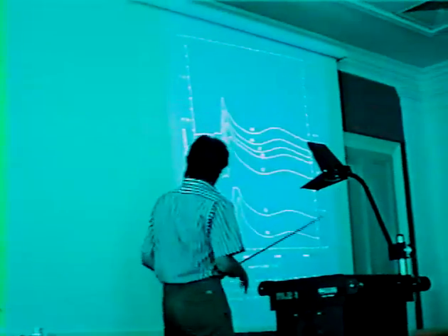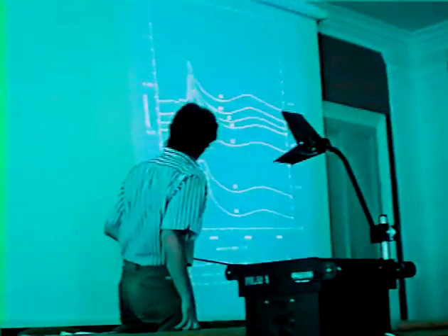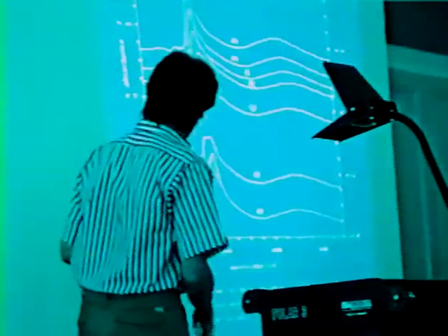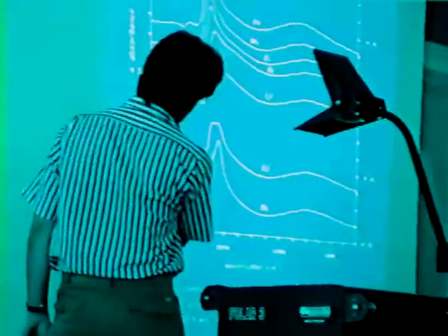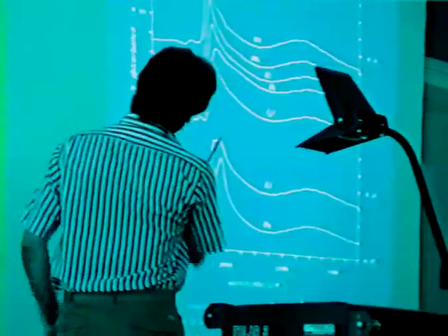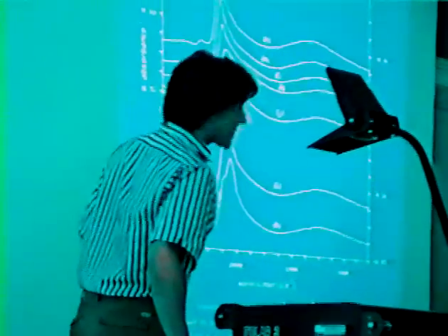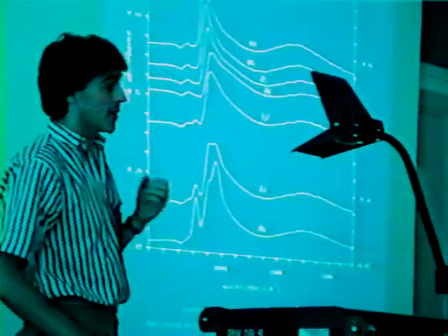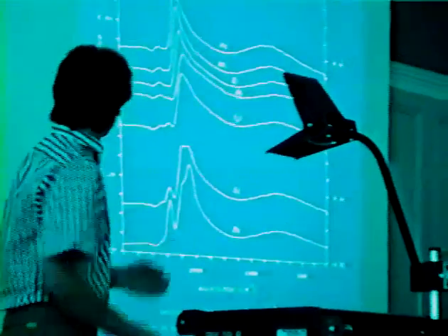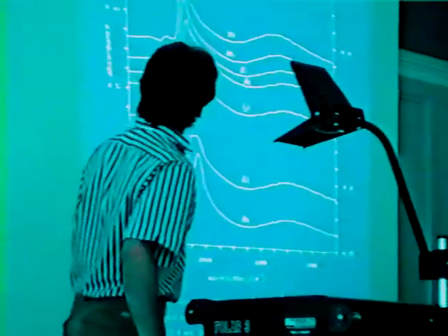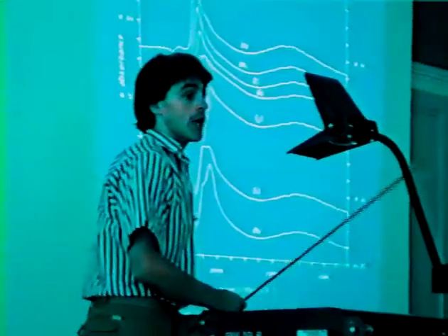Okay. So between about 508 K and 523 K, there is a dramatic reduction in the intensities of the gem dicarbonyl species, and a growth of a new band due to linear carbonyl. If we take this up to 573 K, which was the temperature of the original hydrogen reduction, then we're left essentially with only a linear carbonyl species.